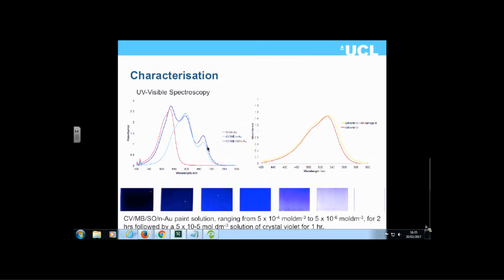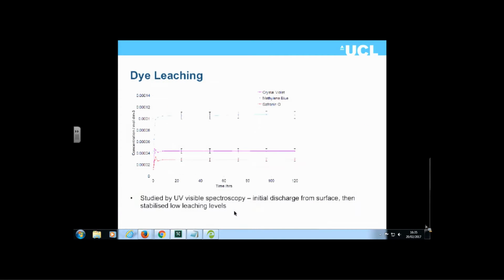This shows some examples of UV-vis spectra of the different wavelengths of the material we've made, and what the color looks like for our crystal violet, methylene blue, nanogold paint solution. When we've made this material, it has very little leaching into the solution, so we think it's a surface contact phenomenon which is responsible for killing the bacteria on the surface.